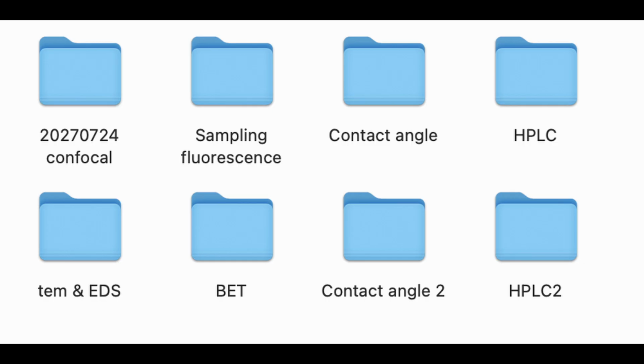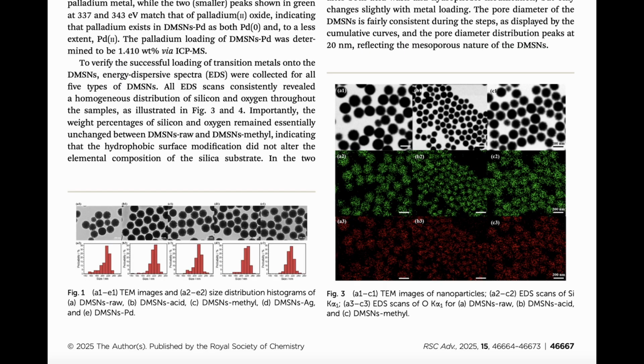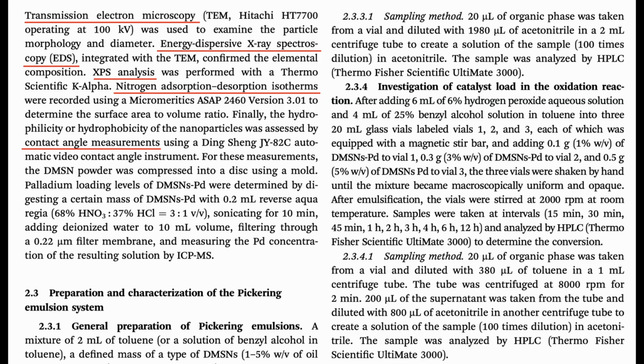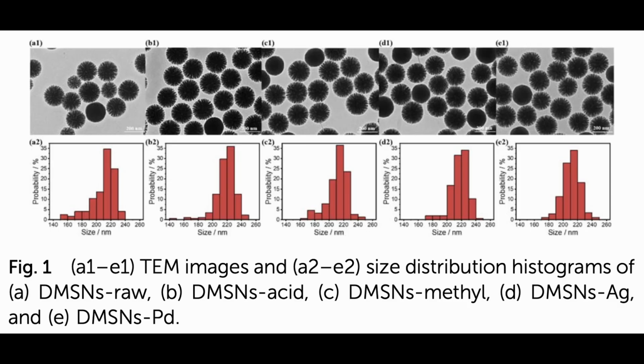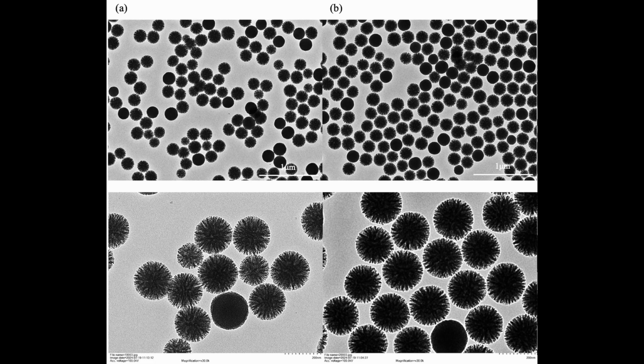Now that the catalyst is made, some characterizations must be done to confirm that we obtained the expected nanoparticle size, morphology, elemental composition, surface area, and hydrophobicity. These variables are examined by various advanced instruments. Transmission electron microscope, or TEM, offers nanometer scale images from which the particles can be visually seen as spherical and dendrite shaped, proving that we indeed made dendritic silica spheres.